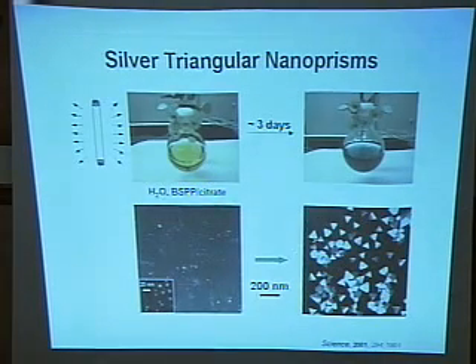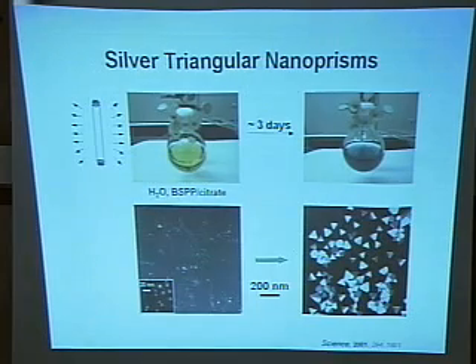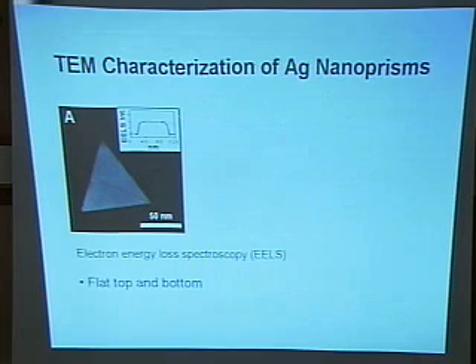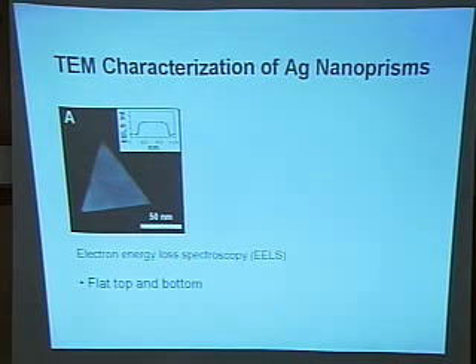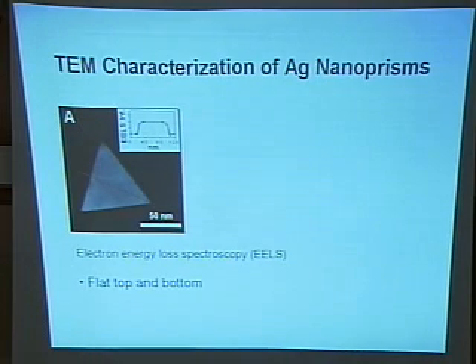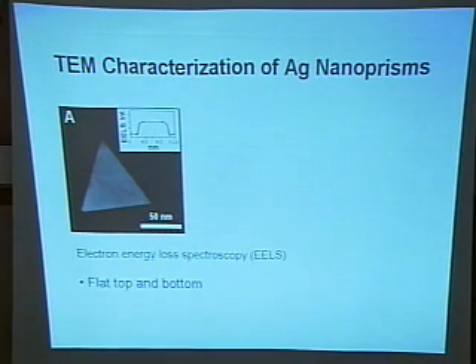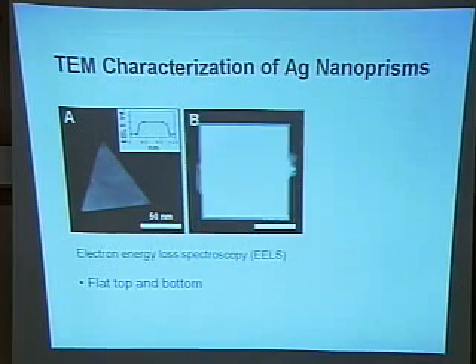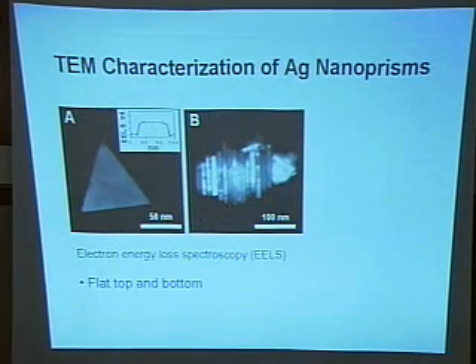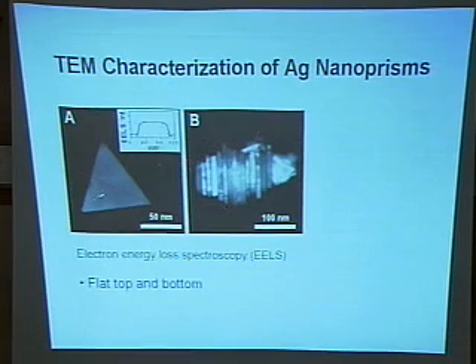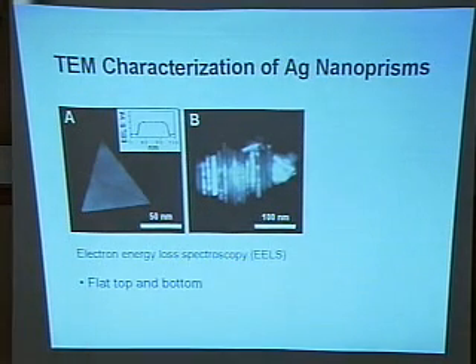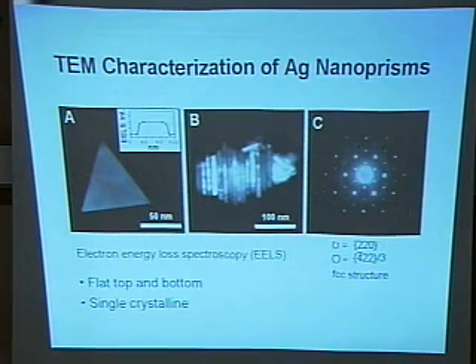We found we get beautiful triangular particles. And each of those particles has a flat top and bottom. Because they're so flat, due to the van der Waals interaction, they tend to assemble and stack here. So you can see the stack. When you turn this, you can find it still is a nanoprism. Each of these triangular silver nanoprisms is a beautiful single crystal.